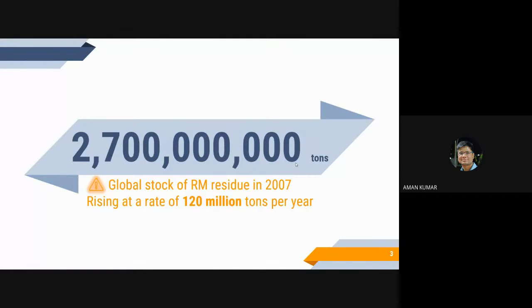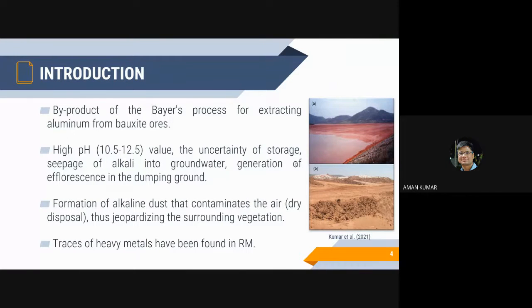The number on your screen, that is 2,700,000,000 tons, is the global stock of red mud in the year 2007, which has since been increasing at a rate of 120 million tons per year. Now, why should we be concerned about this number? Formerly known as bauxite residue, red mud is the noxious byproduct of the Bayer process for extracting aluminum from bauxite ore. It is alkaline in nature and has a pH ranging from 10.5 to 12.5, which is one of the reasons why its concomitant disposal might lead to a number of environmental issues. If it seeps through to the groundwater, it degrades the groundwater and the soil quality, making it unfit for consumption and farming. More so because of the presence of heavy metals in the red mud.